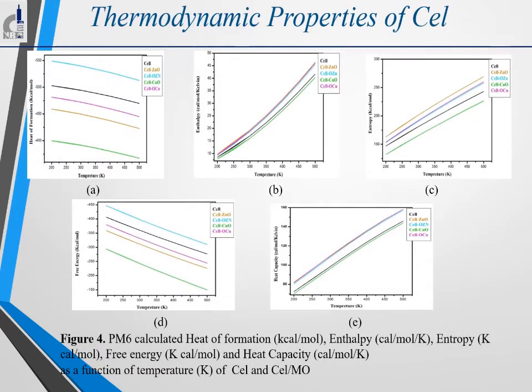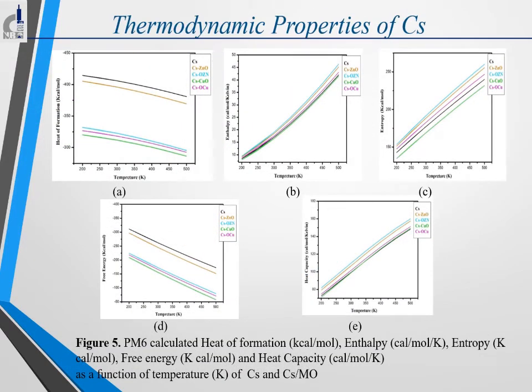Also, thermodynamic properties were calculated for all structures at the same level of theory, such as heat of formation, enthalpy, entropy, free energy, and heat capacity, against temperature ranging from 200 to 500 Kelvin, which describe the thermal stability of the structures. For the cellulose data, the most thermally stable structure was cellulose copper oxide, which has thermally stable behavior with increasing temperature. As well, the most thermally stable structure for the chitosan group was chitosan copper oxide, which recorded stable thermal behavior with increasing temperature.